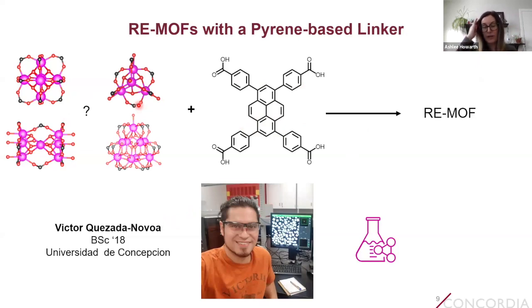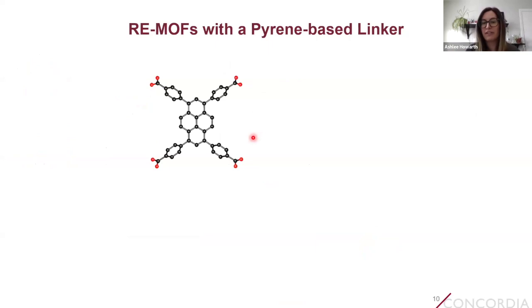But now that we've been working on these MOFs for over 6 years, we understand a lot more about how to make them and how to control certain building blocks and how to make very specific targeted topologies. But at the time, we weren't so sure. So the first thing that Victor did was synthesize the tetratopic pyrene-based linker. He then reacted it with a rare earth nitrate precursor under conditions that we expected should lead to the generation of a high nuclearity cluster node.